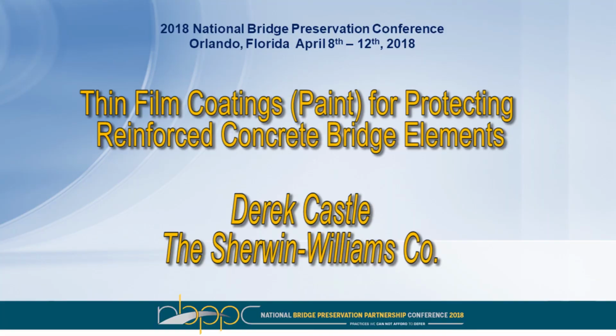I'm wondering if you can combine treatments and you use a penetrating sealer, maybe like Protectosil, and then do your coatings both? Are they compatible? That'll vary manufacturer to manufacturer. I think you should be able to, within a manufacturer, have a particular silane or siloxane-based penetrant sealer, or even an epoxy penetrant sealer, if you so chose, that would penetrate into the concrete and then come back and put an epoxy-based primer and a urethane or an acrylic finish coat over it, belt and suspenders type of approach.